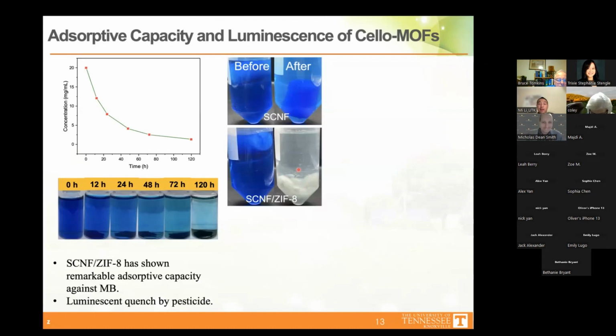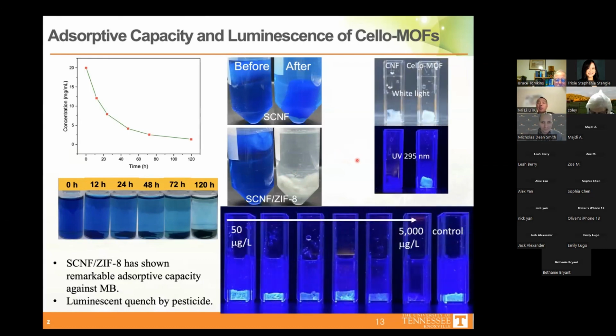Okay, so another interesting thing we did is that the combination of nanocellulose and the MOF can show some sensing function. What I mean right here is a luminescent function. Basically, if you have the cellulose on the left and the cellulose MOF hybrid on the right, under the white light there is no difference between them. But if you irradiate a UV light at 295 nanometers, you can tell the nanocellulose doesn't illuminate at all, but the cellulose MOF hybrid has luminescence.